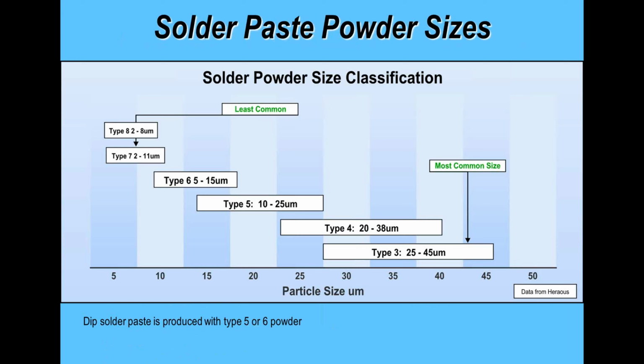Recently, perhaps in the last couple of years, type 4 material has become more popular. There's two reasons. One from a printing perspective, that type 4 materials can have a better performance in terms of printing for ultra-fine pitch, but the disadvantage was that they were more expensive. Generally speaking, now the price has become very close to type 3 products, so again you've got that shift, so you're getting the print performance and the successful reflow soldering of type 4 products without the added cost.